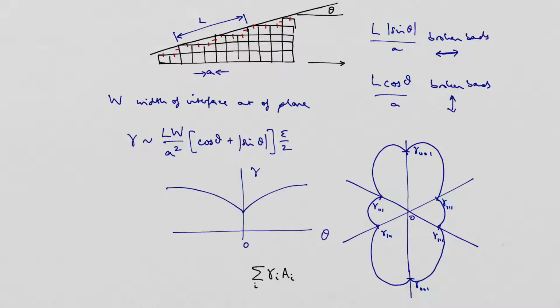Just assume that what I'm doing here is I'm starting from a particular surface, which is not the lowest energy surface, and I'm changing the orientation now. So locally it increases like a cusp. And then I keep doing that, but at some point I find an even better interface that is lower energy than the first. That will have another cusp, but it will be closer to the origin because I have lower energy.